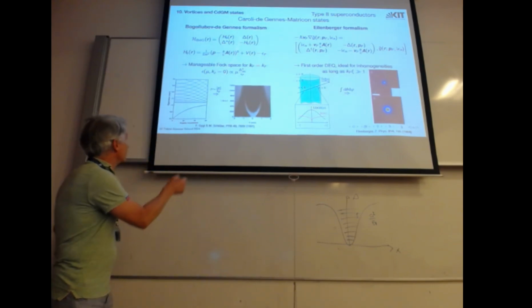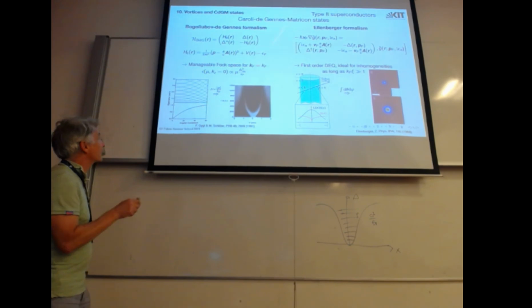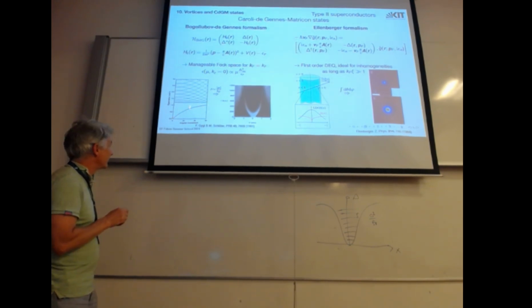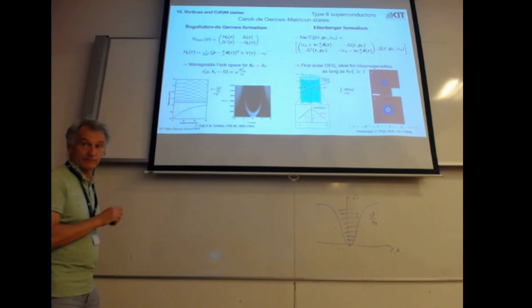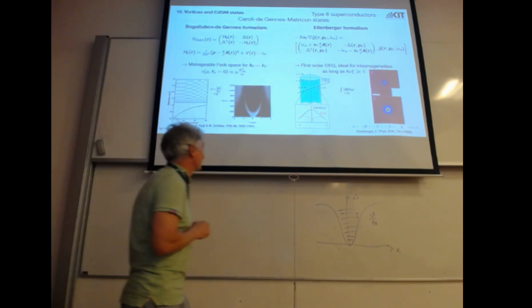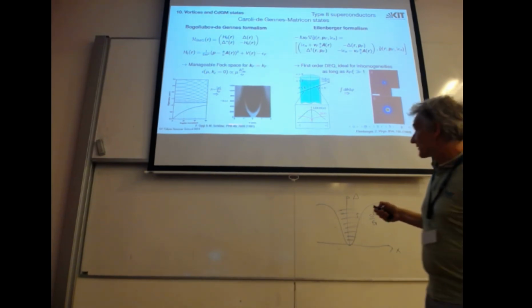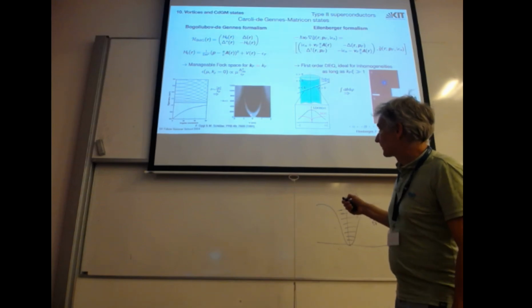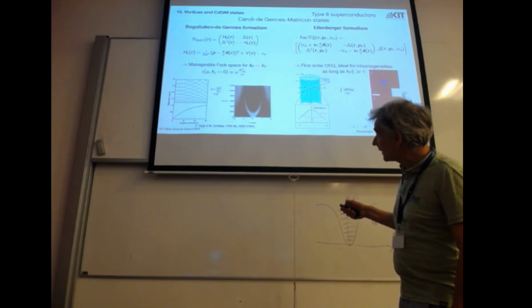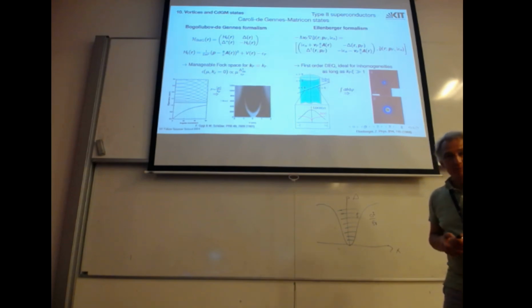So this is the calculation. This is an exact calculation. You have the single particle states above the gap. And inside the gap, you have these Caroli-de Gennes-Matricon states, and they lie very, very close. They've actually made something like a band. So this is a single particle band in this box, with unpaired electrons in the box. Other unpaired electrons are outside this box. This is a calculation of this. Now, if we go out in energy, what is in this part is a round box.